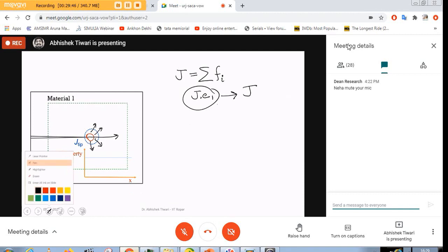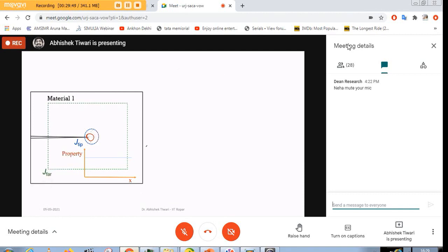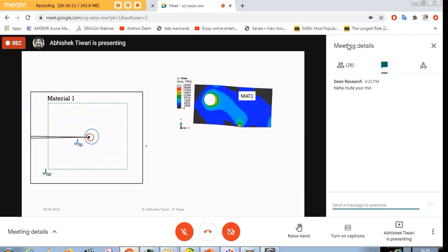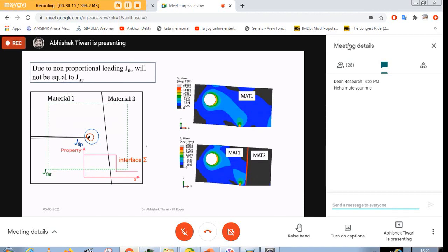So there will be no configurational forces here because there is only one singularity, right? So everywhere else the divergence is getting balanced, and at the tip it is not getting balanced. So we always have one force as long as the material is homogeneous. That means there is no change in the property of the material, there is no singularity, there is only one crack, and there are no holes in the system. But what happens if I have another material and there is a transition from material 1 to material 2? So let us say that material 1, which is on the left hand side, is having a higher Young's modulus, and on the right hand side we have lower Young's modulus. So there is a change in material property, and this will cause a non-balance in the divergence, and we will have configurational forces at this interface.